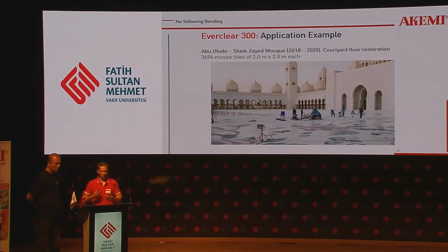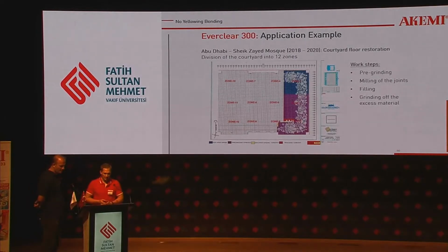So they asked us if we have a solution for that problem, and the problem was also that they can only work at night for this restoration, because during the daytime there were tourists, and also the sun radiation and the heat would be so hot that you cannot use construction adhesives because of the temperature I already told you. So this is a plan of how they did the restoration. They divided it into 12 different zones, and each zone was prepared at night. They ground the whole surface, one zone after the other. They milled the joints, then they filled them, and after that they ground the excess material.